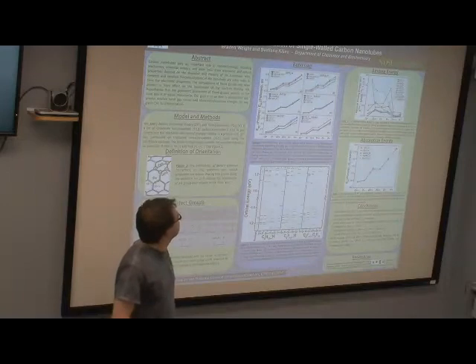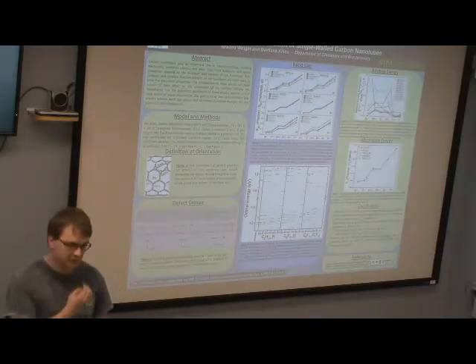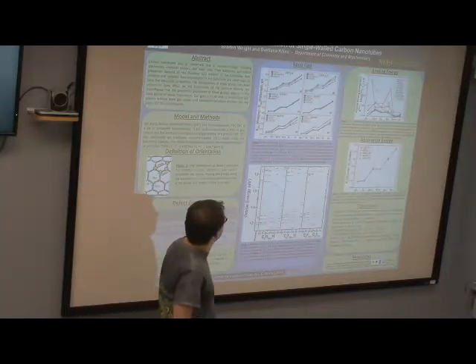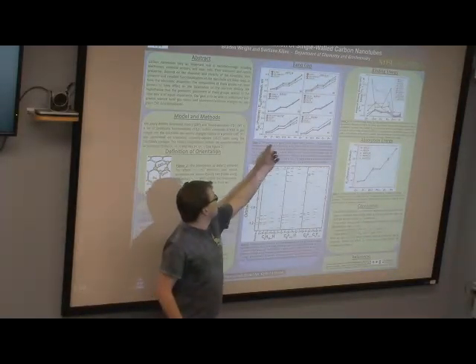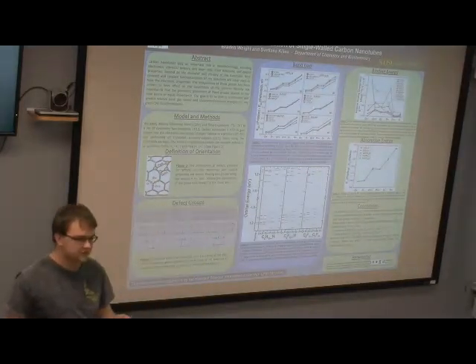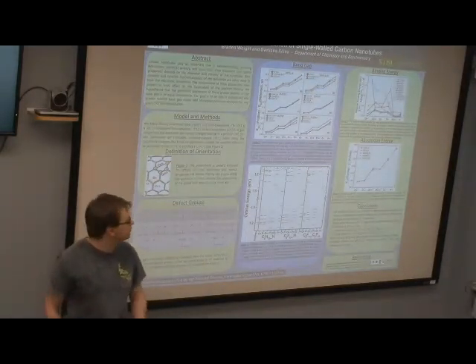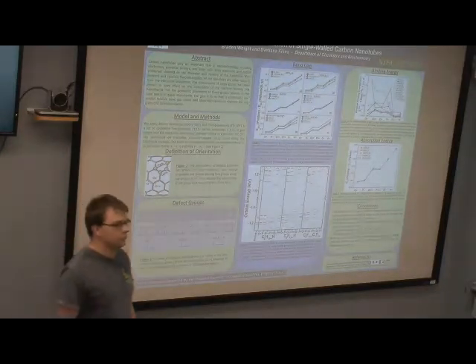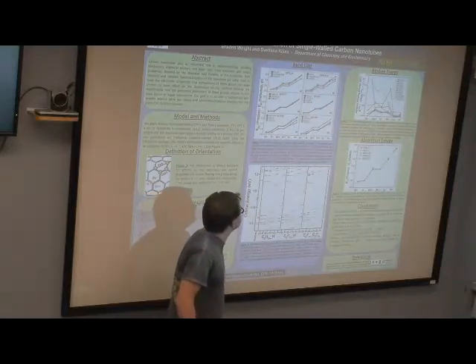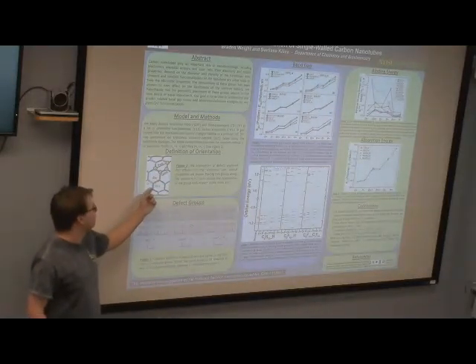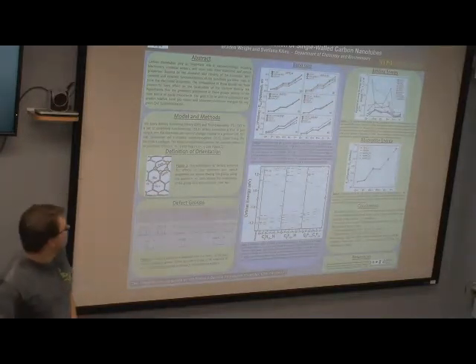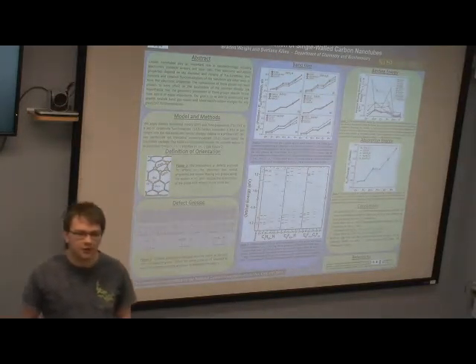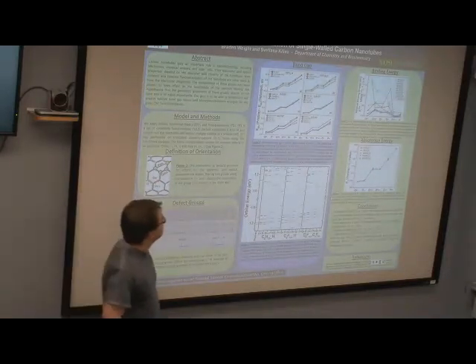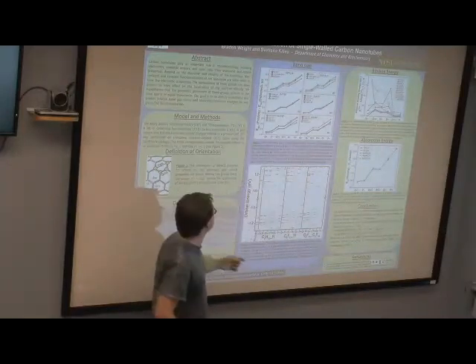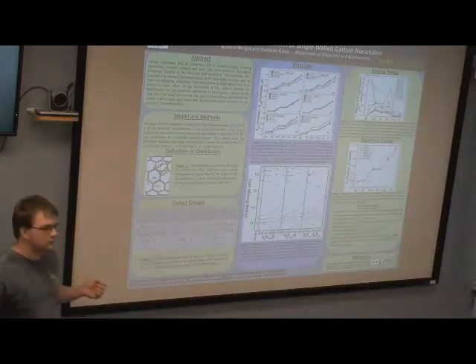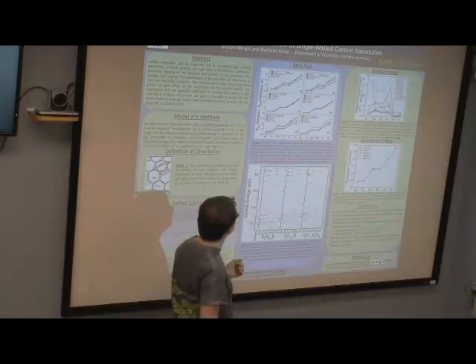So the first thing that we looked at was the band gap change with respect to the functionalization. I have ordered the axis from least change to most change. And most change would be the most reduced band gap, or the most redshifted band gap. As you can see, the O plus direction, so the ortho in the direction of the chiral angle, shows the least change in the band gap with any functionalization. And you can see the most is the P plus, so just jumping across the ring instead of adjacent shows the most shift, so the most redshifted band gap.